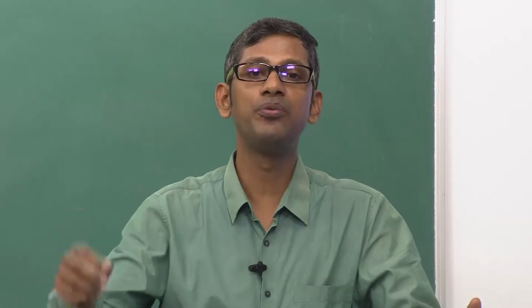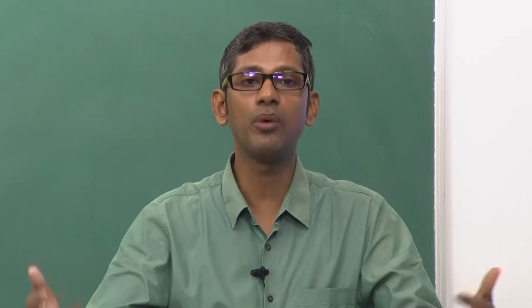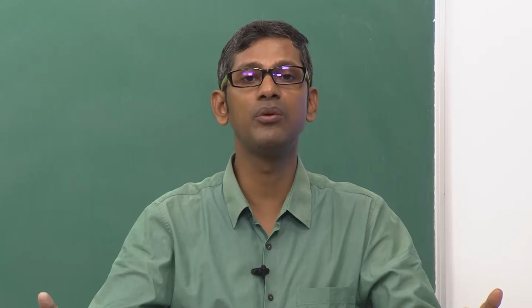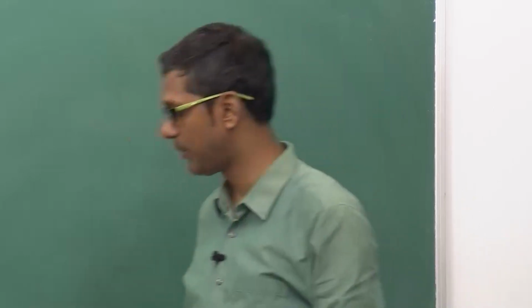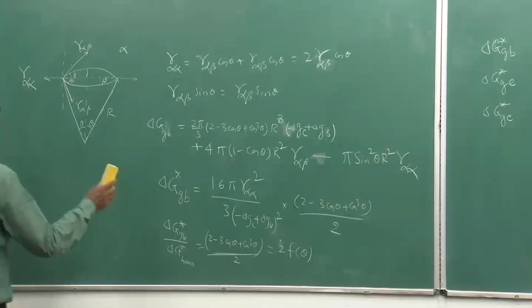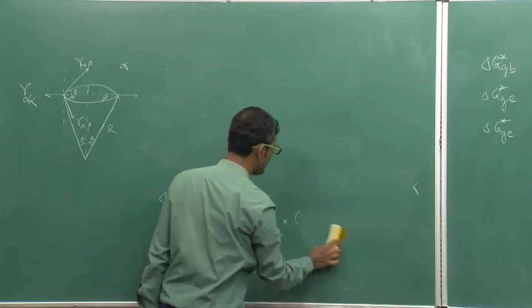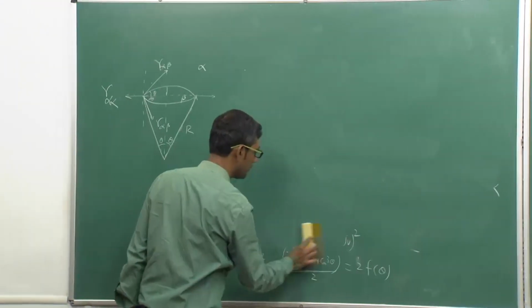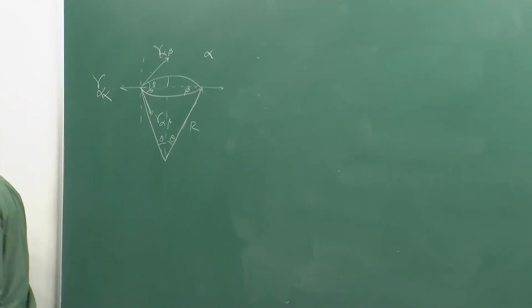Because the dislocation core has a lot of distortion energy. If a new phase nucleates on that, the distortion energy can be relieved, and that's the reason the system can gain a lot of energy if it allows some phase to nucleate on the dislocation. Mathematically how it will look is very simple, again not very difficult. We can consider such a model, but we don't need to do much. What you need to know is the strain energy because of the dislocation, and that equation is available in the mechanical metallurgy books.